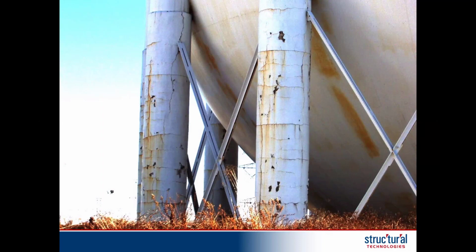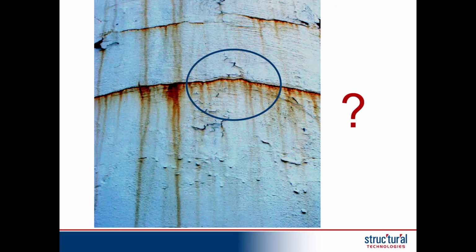But how much is there? The only way we can really tell is by doing these limited excavations. They're typically 6 inches by 6 inches, so we can get in there. And what's interesting, you can tell from this photo, in excavation, we can see areas that had corrosion very defined at certain levels. The region above it is almost pristine. The steel is uncorroded. There's even still galvanizing on the mesh that's within the fireproofing. But as soon as you get to the lower line, you see the pitting corrosion, and the galvanizing is off, and even the mesh is missing in many regions.